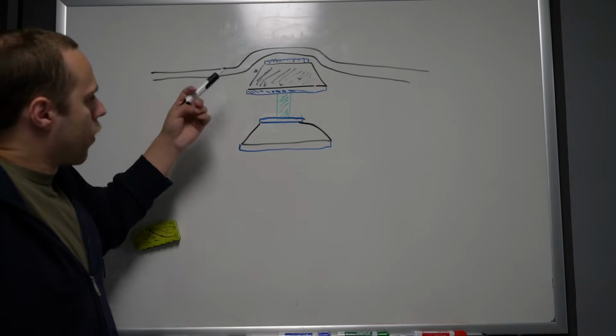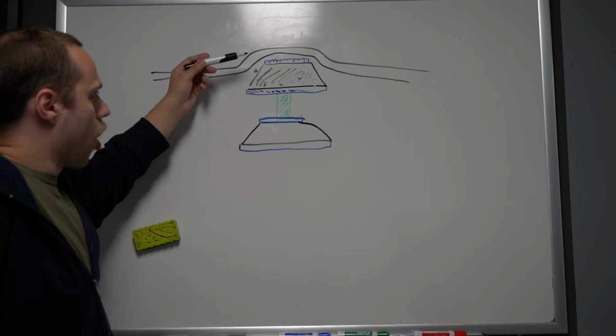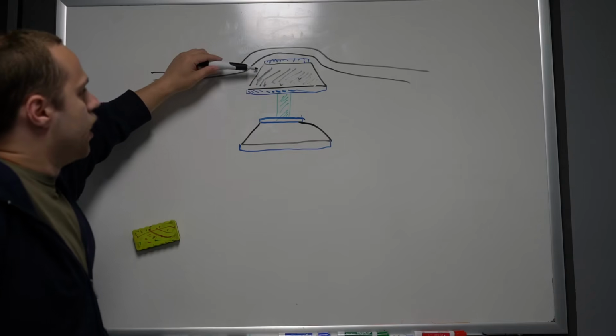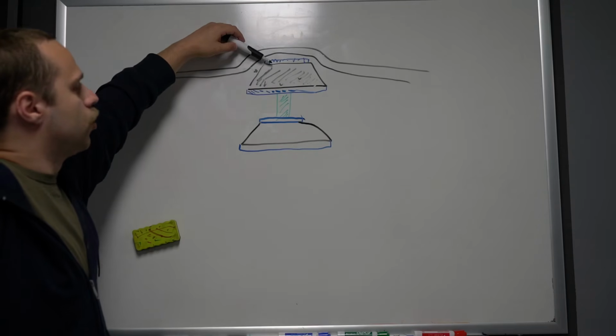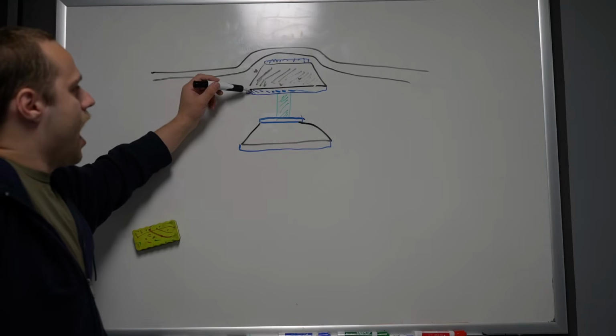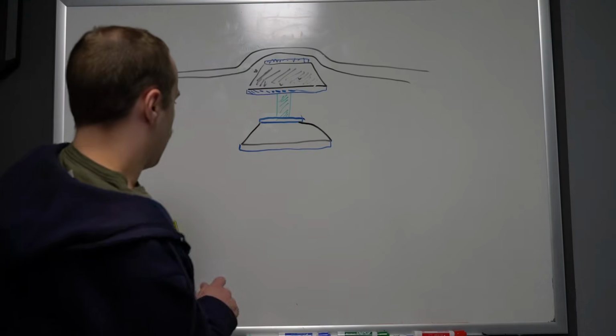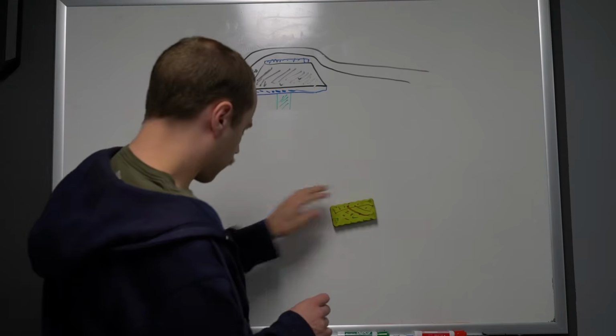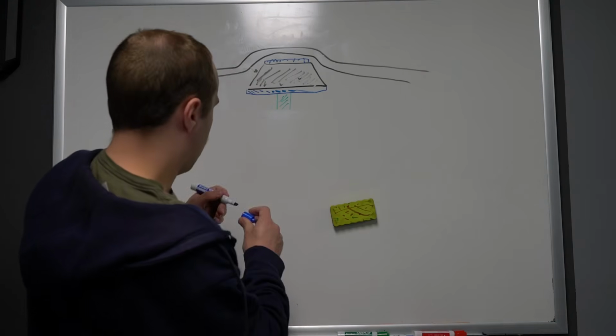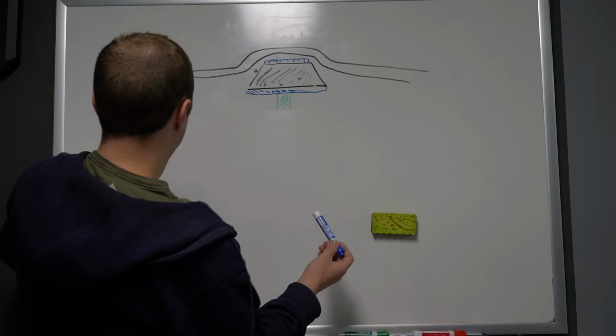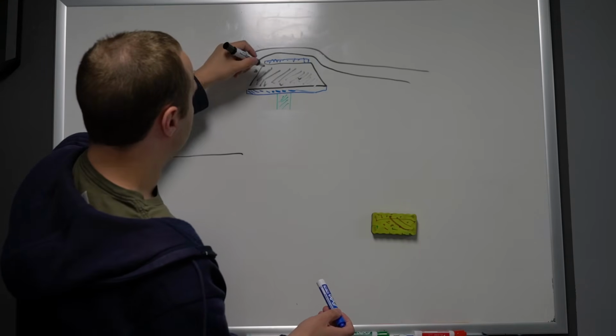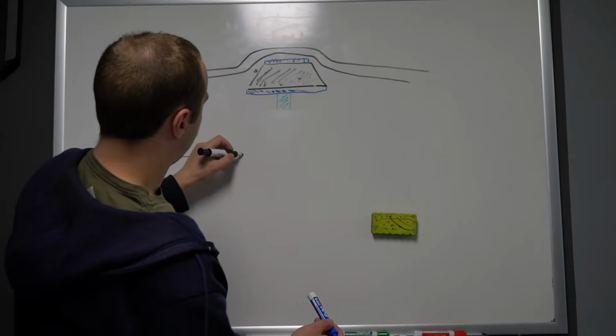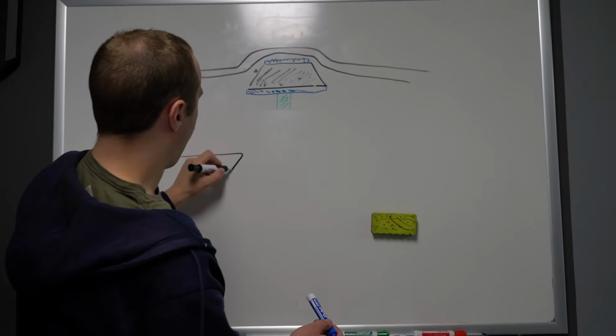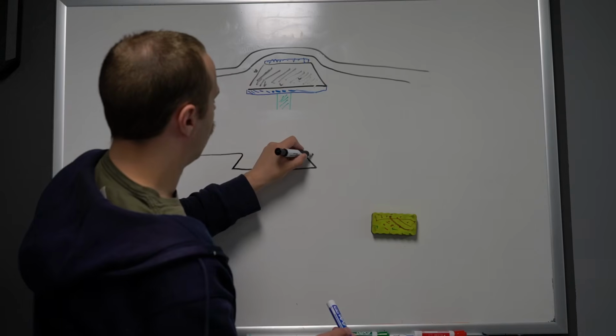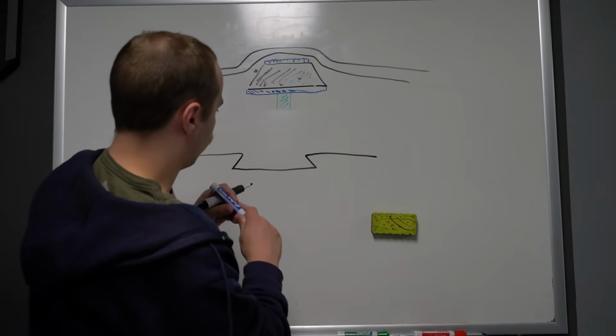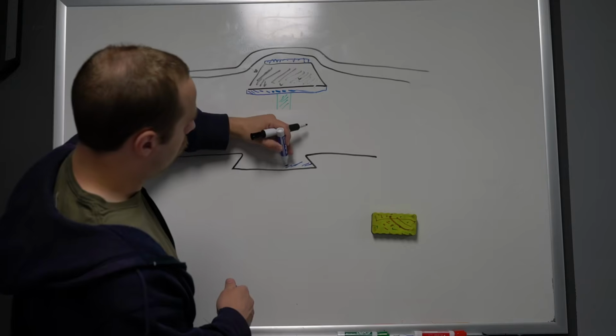But for our purposes, for the most part, what we're going to be getting is aluminum fluoride, which should dissolve into the etchant. And now we're going to have this unsupported top layer, which will just float off because there's nothing holding it in place. And now, if we erase this, what we get is our dielectric layer. We've now eaten away some of the aluminum, so we've got this hole where the aluminum was, and we've got our titanium nitride at the bottom.